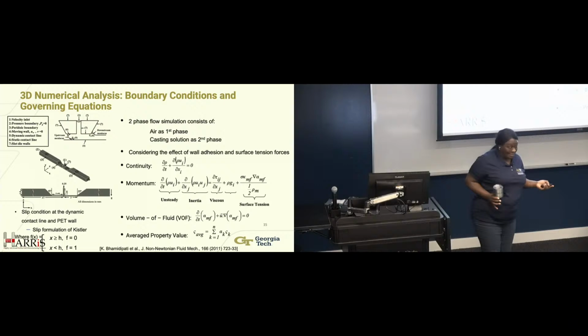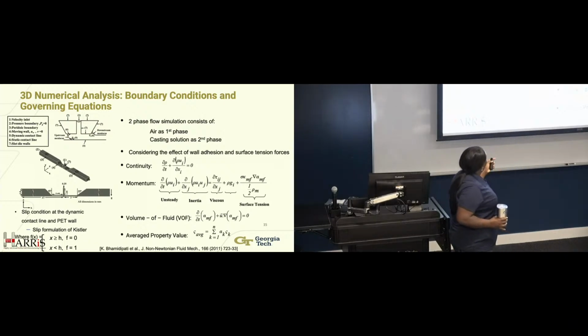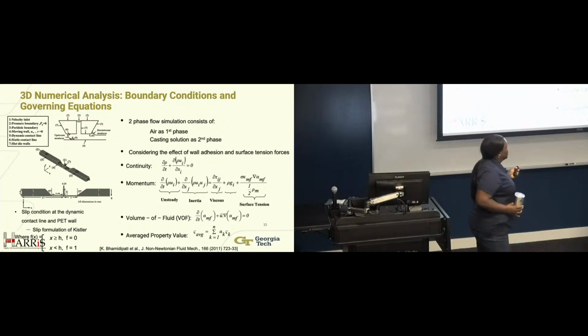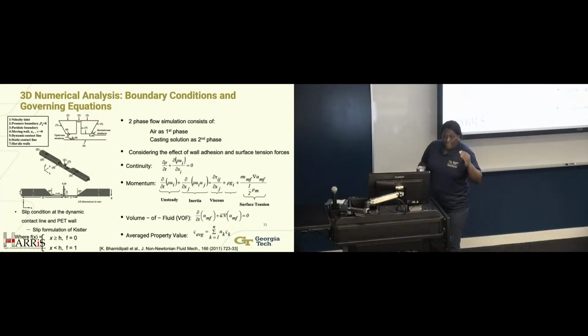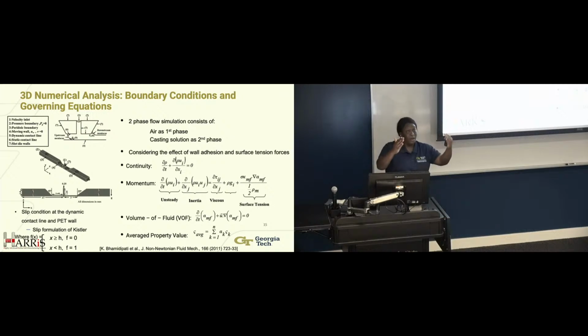Again, we do computational analysis as well as experimental. And so I'm going to show you a comparison. These are some of the boundary conditions and governing equations that we look at whenever we're doing this work. So we have two phases. We have the air, and then we have the solution. We're considering the effect of wall adhesion, surface tension, continuity, momentum, volume of fluids, and then the average property values. So with this set of equations, what we can then do is compare, because think about it, you can't do experiments indefinitely. So we need to come up with a framework where we can actually test at the highest speeds possible, but know that our data is accurate.